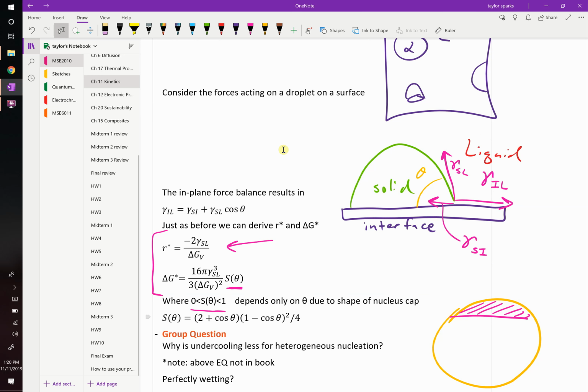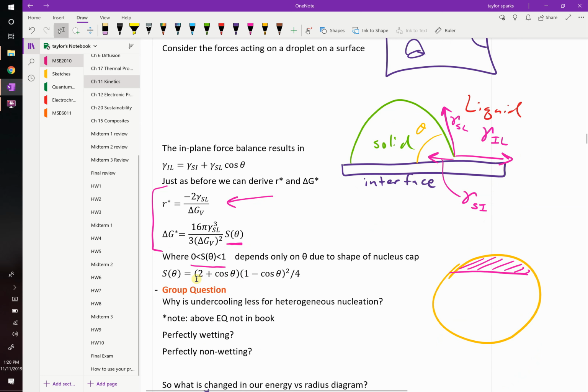And then all it is after that, this formula here for S of theta, that's simply the formula for the cap of a sphere. And that cap, we could define it at different spots, right? It depends on what your wetting angle is. Maybe it's that much. Maybe it's just the very top. And that's going to change how much of a benefit you see from heterogeneous nucleation. So when you do something like cloud seeding to get rainwater, you'd want to choose the surface energy of the material that you use. First off, it's cheap. It's non-toxic, right? It's okay if you litter it over a bunch of population, right? It's not going to kill people or mess up anything. But it also gives you something that looks the most like a spherical cap, because that's going to give you the biggest benefit. Okay? All right.